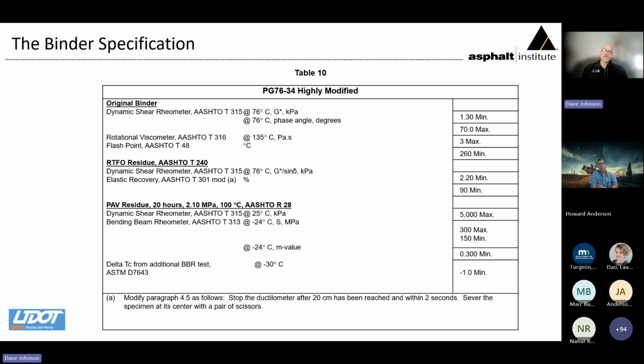For those who might be interested in the Utah spec, you'll notice that it's very heavily aligned with the AASHTO M320 spec. Howard, would you point out any changes that you've altered from the 320? Yes, we have the G star spelled out separately from the phase angle, and the G star is put at 1.3 to make sure we're in a good position there. And we also have the elastic recovery at 90% minimum. We do cut the sample immediately within 2 seconds. So this 90 minimum here would represent about an 85 if you follow the AASHTO procedure.